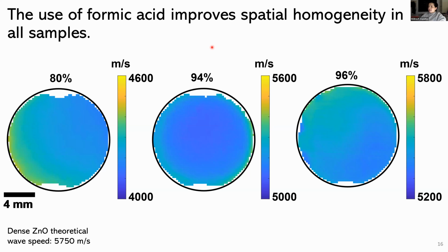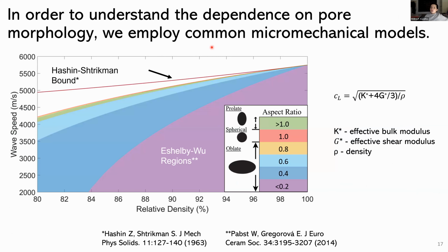So this was all great in identifying individual samples and their variations, but what we really wanted to do was now understand on average, so some of these average properties, why weren't these samples matching up with what we would expect for a fully dense zinc oxide sample. So what you're going to see in the next couple of slides is that we actually started to look at some micromechanics models to understand the effective elastic modulus of each of these samples relative to the shape of the pores that were within them.